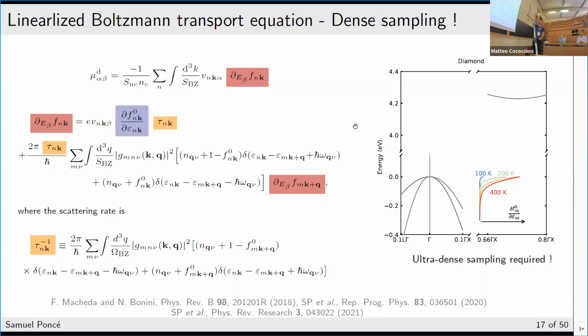Now, if you derive this with respect to energy, it's an extremely peaked function. So here I'm showing the function as a function of the energy, and you can see that this is only 0.2 eV, so you are at the edge of the valence band of diamond, or the edge of the conduction band of diamond, and you can see that basically this term will only contribute extremely close to the band edge. And so for this reason, you need very, very dense k-point and q-point grids in order to converge that calculation. And so this makes it extremely difficult to compute because you need extremely dense k.